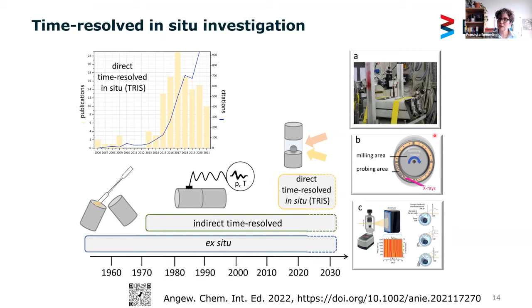So there are improvements to this setup. Here, the colleagues from the PSI, they have a ball mill with an outer ring where the sampling happens. So you get high quality data for these investigations. A little drawback is that you cannot monitor reactions where you use tiny amounts of liquids. And that is a recent update we did, and I will come to that in a second.